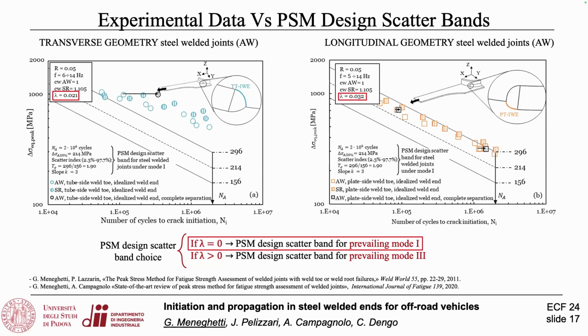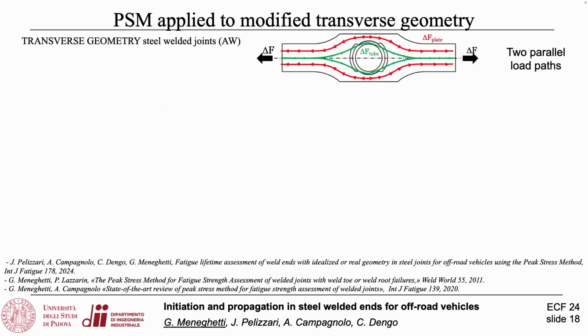And the explanation came from here. These are the specimens we tested until the crack initiation criterion was satisfied, plus 0.1 millimeter of the hydraulic actuator, and we proceeded the fatigue test until the final separation. You see a very long fatigue life if compared with the same situation for the longitudinal geometry. And the reason for that is that for the transverse geometry, indeed, we tested two welded structural details in parallel.